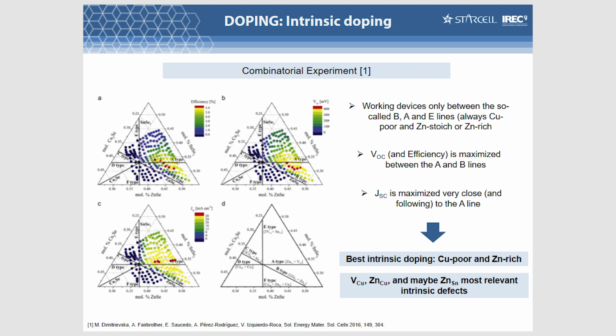So I was speaking about intrinsic doping. What we found is that most of the working devices actually fall into the region that Susan predicted as the most interesting one, where kesterite shows only shallow defects in principle. And this is observed here. It's between the A, B, and E type lines, where you obtain the maximum efficiency, the maximum VOC, the maximum current of the devices. This gives us the input that we have to work. Actually, this is the experimental demonstration that this is the most relevant composition.